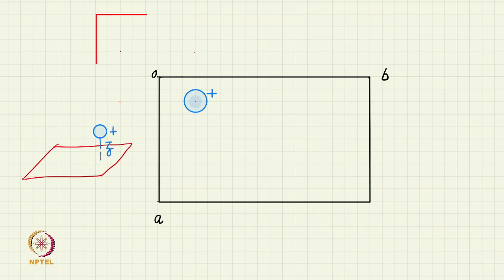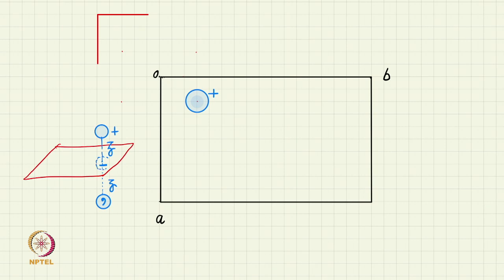So, I am writing it as plus, but then if I reflect it, it will go below the mirror plane and will also change the handedness, and changed handedness in the crystallographic notation is shown by a comma. So, I represent it by a comma and below this plane. Now, if it was at a height z above the mirror plane, then it will again be exactly at a height z below the mirror plane, the image point.